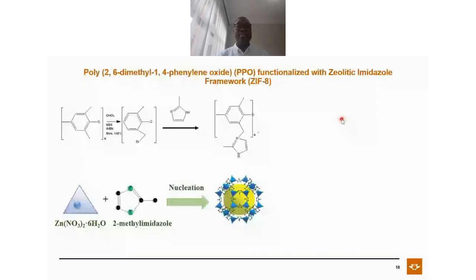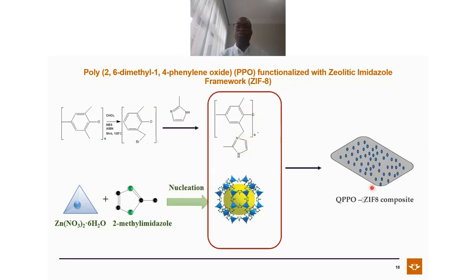We also did exactly the same thing, but this time we used what you call a ZIF, a zeolite imidazole material. We wanted to see how it performs. We used graphene oxide, now we want to see how this performs. We did exactly the same thing, but this time we did not functionalize the ZIF because the ZIF already contained imidazole, so there's no need to functionalize. The nice thing about the ZIF is that the imidazole is part of its original structure, so it's hard to degrade it. In this case, we use a PPO membrane and we functionalize with imidazole. We also combined these two and made what we call a quaternized PPO ZIF-8 composite membrane.